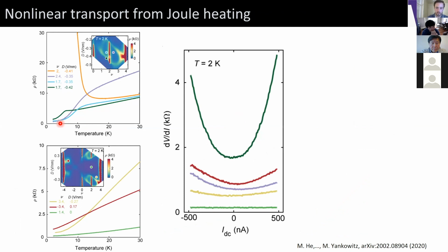So one thing that we want to do first to rule that out is ask, is there characteristic nonlinearity when we measure transport as a function of a DC current bias? And it turns out that the answer is yes, these things are nonlinear, but we think that they are not actually nonlinear in a way that's indicative of superconductivity, for 2 reasons. One is that the nonlinearity persists not just within regions inside this halo where we see these abrupt downturns, but also in regions outside this halo region completely. So for example, this burgundy and this yellow curve are not within these evidently correlated regions, and yet they still exhibit not unsubstantial nonlinear transport. Whereas in contrast, if we go to a very metallic region, we do see linear transport.